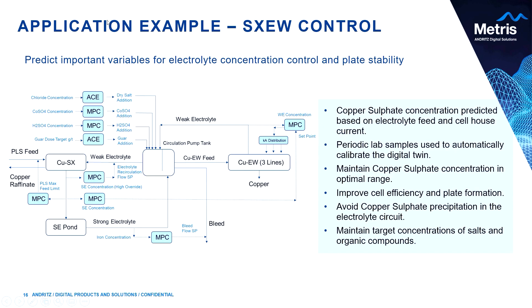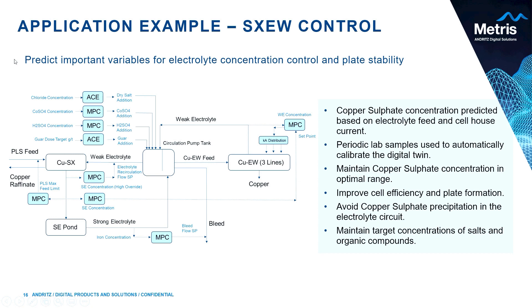The final application is on a solvent extraction electro-winning (SXEW) circuit, where the primary control variable is the copper sulfate concentration in the cell house. Cell house efficiency depends on this concentration — too weak and the cell loses efficiency, wasting power as heat; too strong and copper sulfate can precipitate in the piping circuit. The problem is that copper sulfate concentration is only available from a lab sample every few hours, while the cell house constantly requires adjustments for cathode removal, stripping plates, and power and current changes. The digital twin tracks actual concentration continuously, allowing automatic regulation of strong electrolyte addition to maintain optimal concentration. Additionally, inorganic salts and organic chemicals must be maintained in the circuit for optimal cathode operation, and the digital twin helps ensure those values are met. Thank you very much — that concludes the presentation on digital twins.